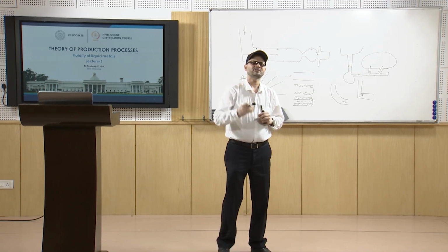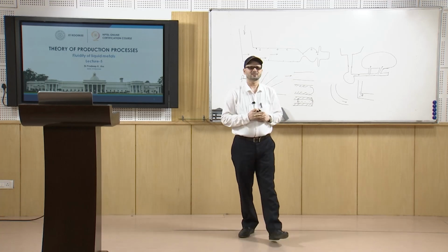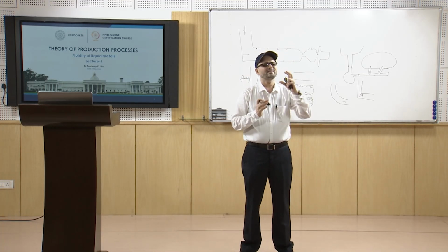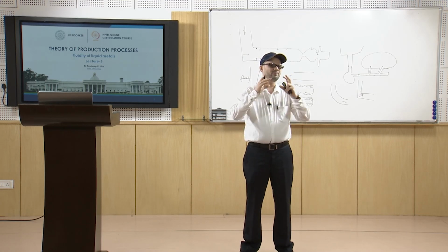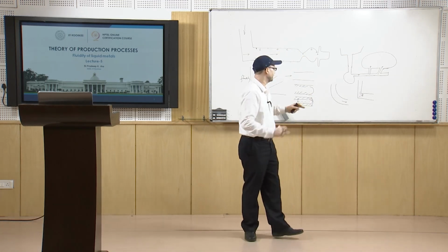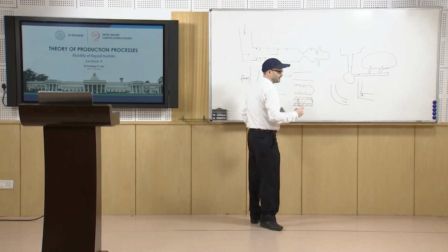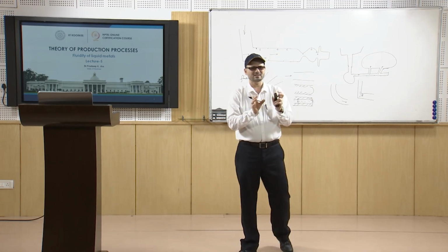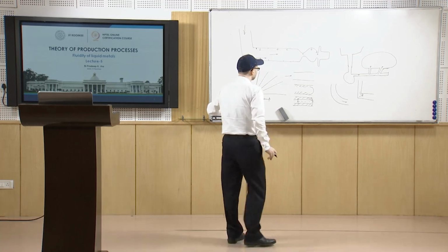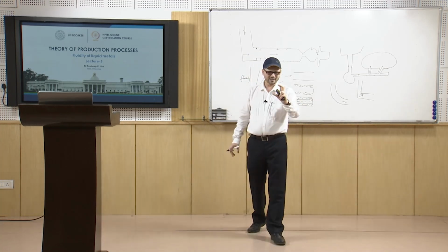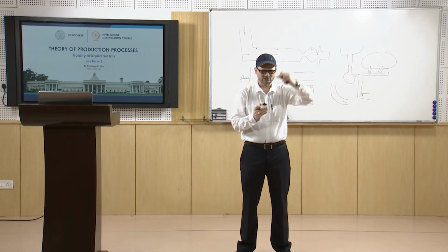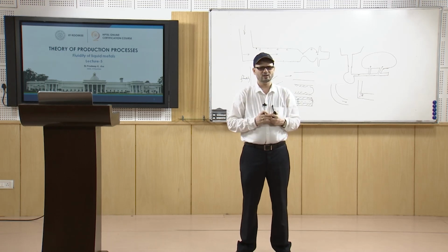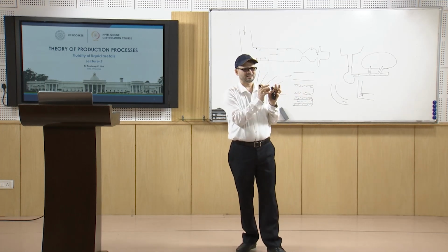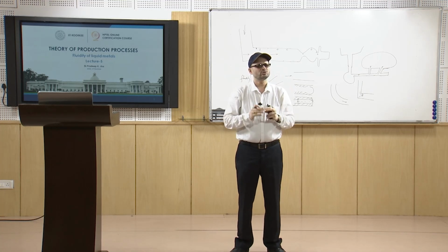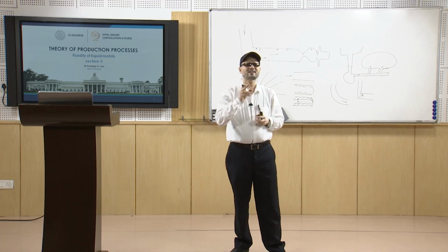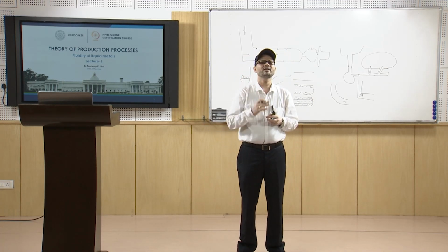Whereas, when you have the dendritic structure, there may be dendritic interlocking, and the dendritic interlocking will affect the fluidity. It will break, in some sense, the movement of the liquid metal, because the dendritic arms may interlock, and that will affect the velocity of the liquid metal which has to go. Here you have smooth flow of liquid metal through these passages, but if you have dendritic formation in the region ahead of this front, as we discussed in the case of constitutional undercooling, that will be a resistance in the path of liquid flow. So, that affects the fluidity. Fluidity becomes less.